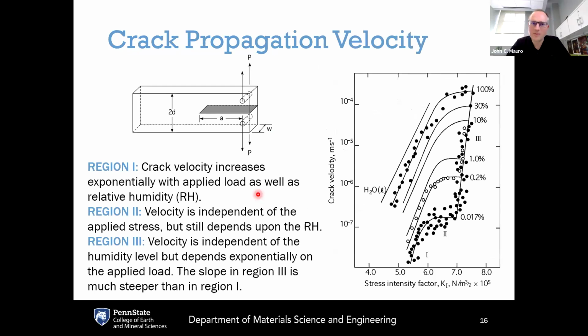That ends up compromising the strength of glass. In fact, one of the famous plots for crack propagation velocity in glass is shown here on the right. It shows the crack velocity as a function of the stress intensity factor, and you can see there are three different regions. Region 1 is slow crack growth, where the crack velocity increases exponentially with applied load as well as relative humidity. Here you are limited by how fast the water molecules can react with the crack tip. In region 2, the velocity is independent of the applied stress, but still depends on relative humidity.